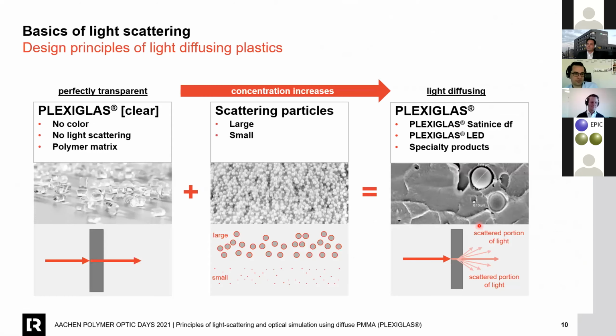What are we doing to compose our diffuse materials? The best way is to use a clear plastic matrix polymer, no color, no light scattering. And then you introduce particles by a compounder, a twin screw compounder is preferred. These are real pictures of particles. You can introduce large particles or rather small particles, and then you get something like that. This is the matrix, and here you can see the incorporated particles. Our satinized DF products contain the large geometrical scattering particles and the LED range contains these small particles. And that's what we are doing, and our customer takes the pellets and molds them into diffusive parts.